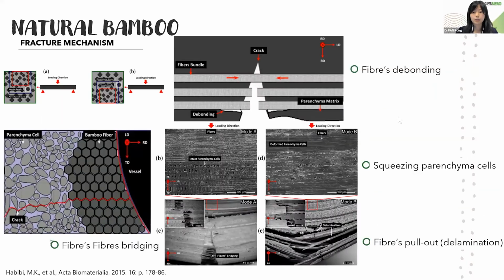And we did the microstructure check of the total structure again. So this is model A, and this is model B. From model A, we can find that it has fiber bridges in this area, from the large picture and also the smaller picture. We can also show they have the same phenomenon. But for model B, we can say that the fracture mode is more like fiber pull out. It's named delamination.